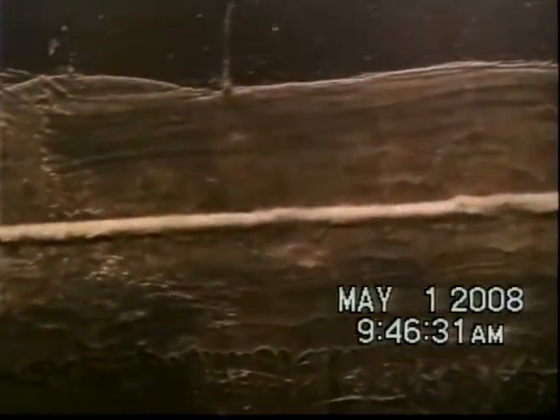Delaminating coating is not present on ring number 4. Note the isolated coating blisters. Once again, the blisters have not ruptured. Another view of the transition from coal tar enamel to super tank solution. The bulk of the coating at the transition is in good condition.